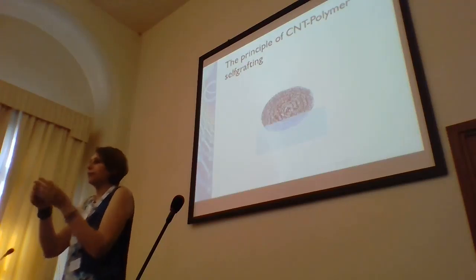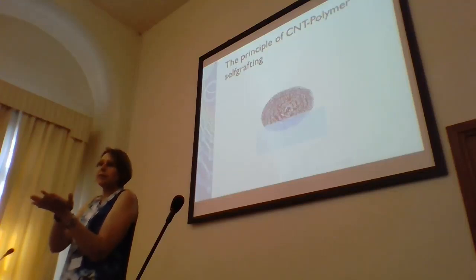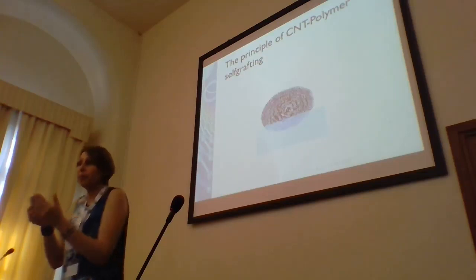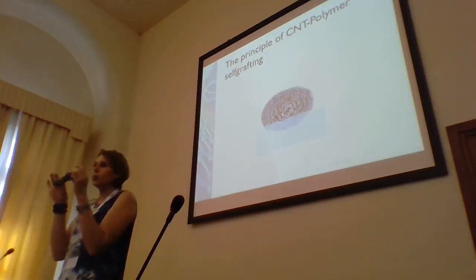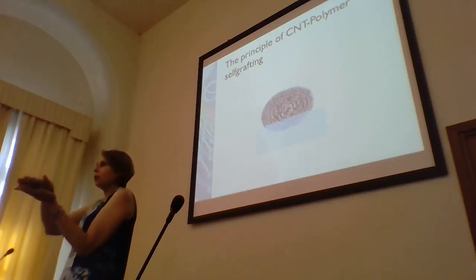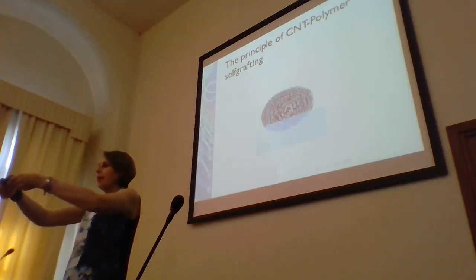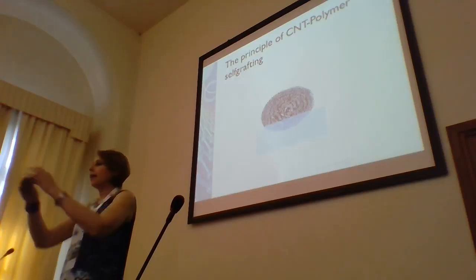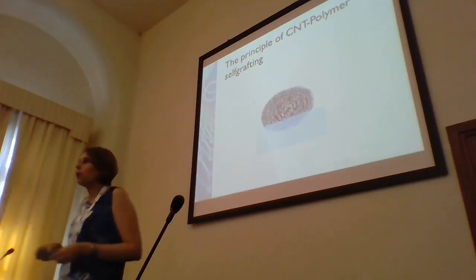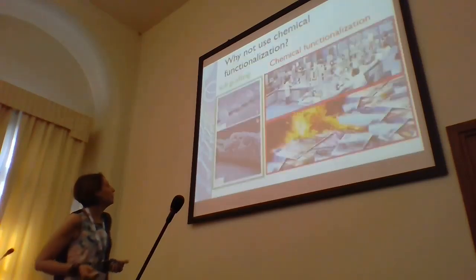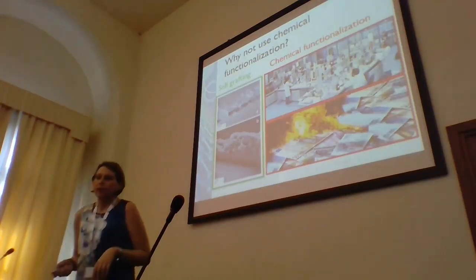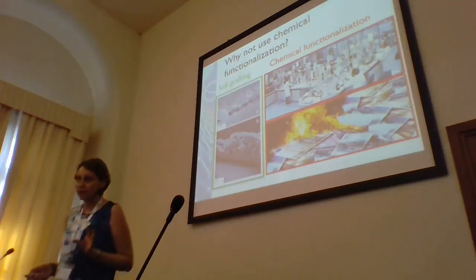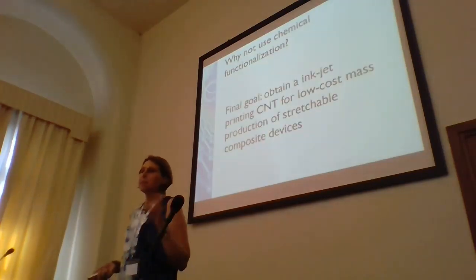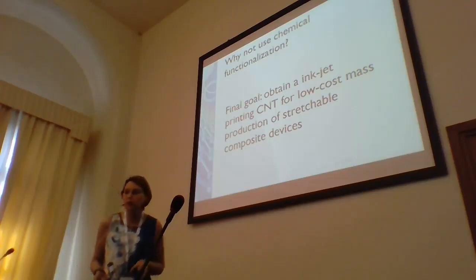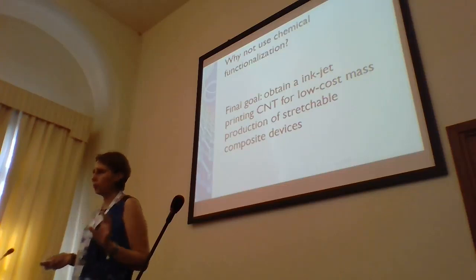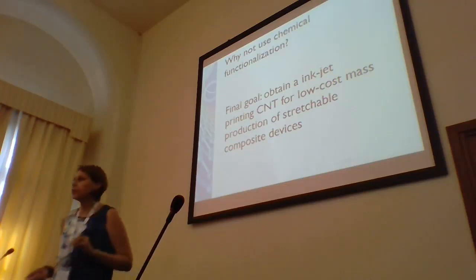You have to imagine this substrate. This is a moldable substrate because the polymer is heated near the melting point. And this is a bundle of carbon nanotubes. When you put carbon nanotubes on the polymer with drop casting, you can obtain this. I can flex and stretch and obtain a conductor that resists the strain. Why not use chemical functionalization? Because it's more complex and more expensive. We would like to obtain, as a final goal, inkjet printing of carbon nanotubes for low-cost mass production of stretchable composite materials. So low cost is an important point of this research.